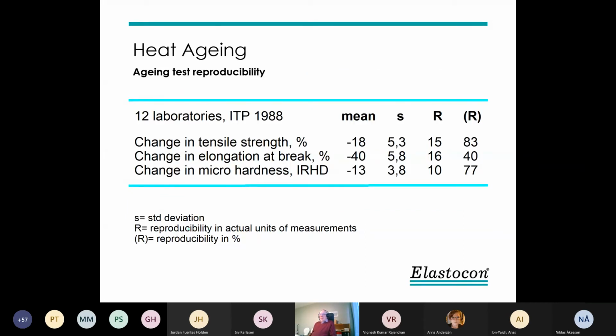Among other things, we made an interlaboratory test program. It means that we compared the results of, I think it was, 3 materials and 12 laboratories, and we measured tensile strength and change in hardness. Here is just a kind of average summary of all results. You can see that for tensile strength, the mean change was minus 18%,